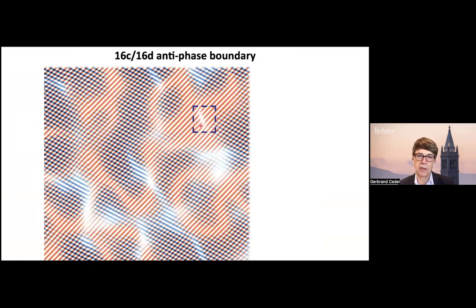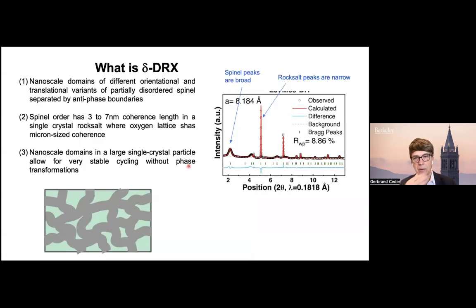So here you're actually seeing 2 domains that are orientationally the same, but they have a shift in 16D, 16C occupation. You actually see beautifully here how the lattice fringes shift. You have an antiphase boundary. So what is delta DRX? It's essentially nanoscale domains of different orientational and translational variants of partially disordered spinel, and it's separated by antiphase boundaries.